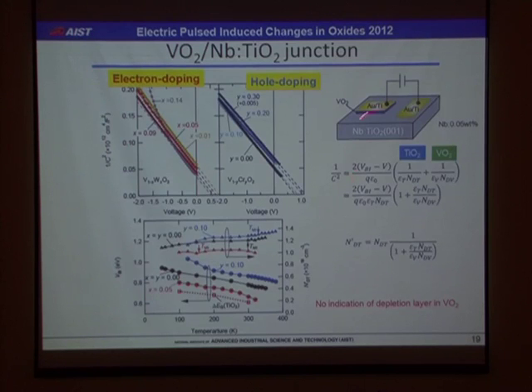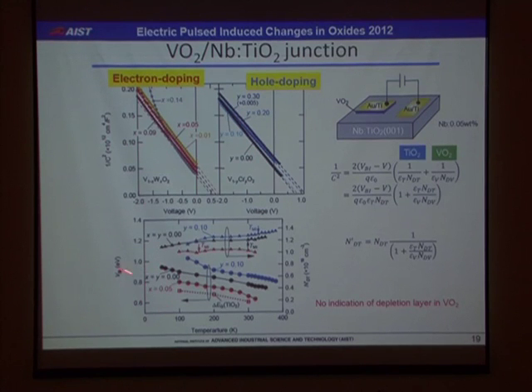So we fabricate this kind of junction structure, and we measure the capacitance of this junction, and 1 over C squared is plotted as a function of voltage. This is the case of electron doping and hole doping. And as you can see, by electron doping, the built-in potential is decreased, and on the other hand, it's increased in the hole doping case. And here, the temperature dependence of the built-in potential and nominal donor carrier density are plotted.